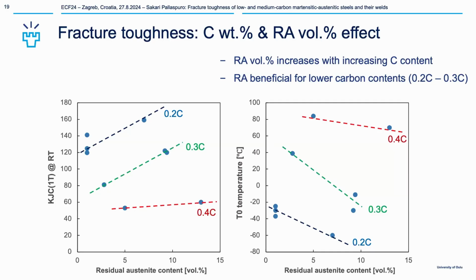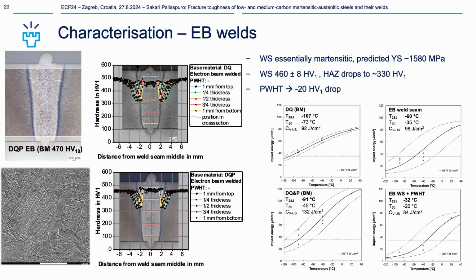So if we want to take a few short take-home messages, how much time do I have? Time is 1 minute. Okay, good. Basically, these high carbon, medium carbon materials are completely insensitive because of this blocky austenite embrittling these materials. But when we have moderate carbon contents, we can still improve these properties as long as those are laminar microstructures. And then I will apparently run a bit over.